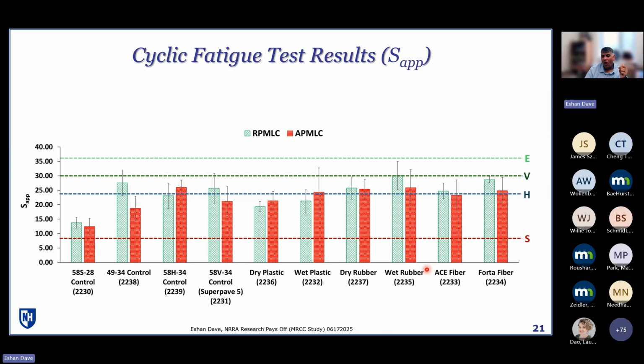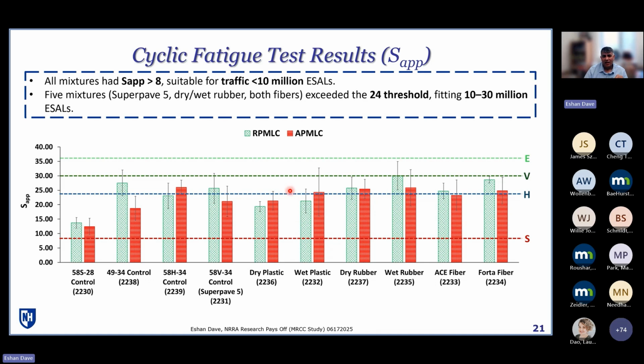As you can see, all of these meet and exceed the standard. Most of them get to the heavy as well, which would really be the case with the traffic levels that we are seeing in this particular case. So that's the threshold of 24 corresponding to 10 to 30 million ESAL type of loading conditions. And most of them retain that even after aging. Once again, the clear distinction is the control. Control was always substantially short-falling in value as compared to almost all of these modified materials.